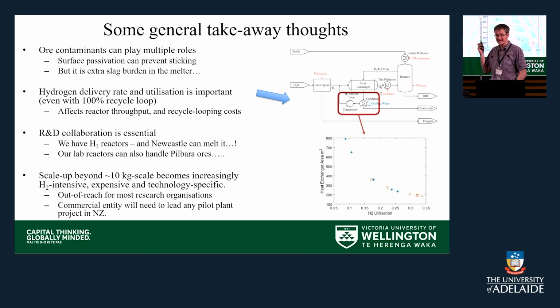So you need to put it through a condensing heat exchanger, which in principle sounds reasonable. But that needs to actually be able to handle some relatively high flows of material. And particularly if your utilization rate isn't up there, they can get really big. Hundreds of meters squared of heat exchanger per ton, which is really quite large. So bearing in mind that gas utilization really matters is something that's come out of the modelling work we've done on this and is, I think, more generally applicable outside of the work we're doing.